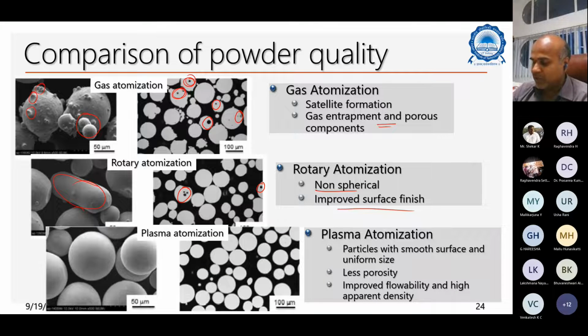The best powders you get are from plasma atomization. With plasma atomization, you get very, very rounded particles, fantastically rounded particles. And you see that most of them have a uniform size, with less porosity or no porosity. At least this image shows that there is no porosity, but you cannot claim that based on this particular image. The porosity is very low.